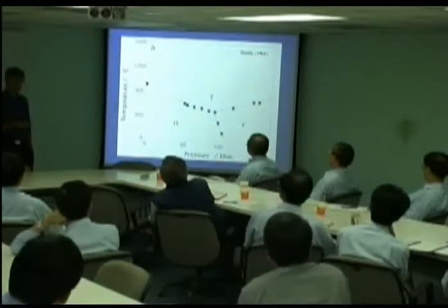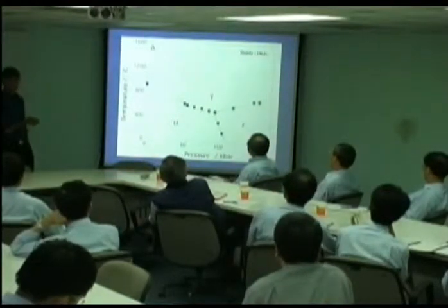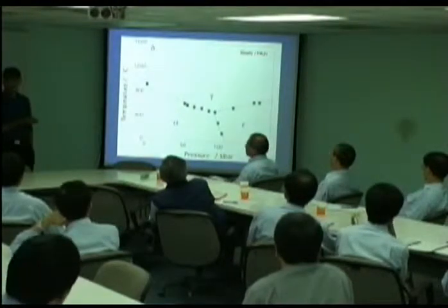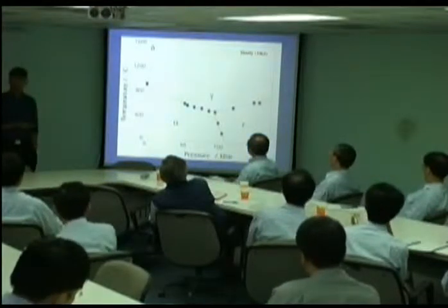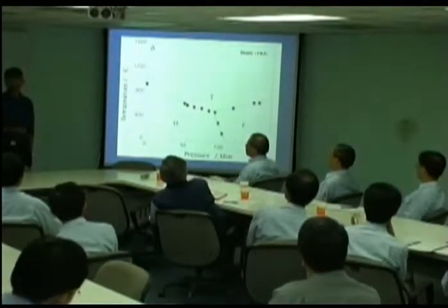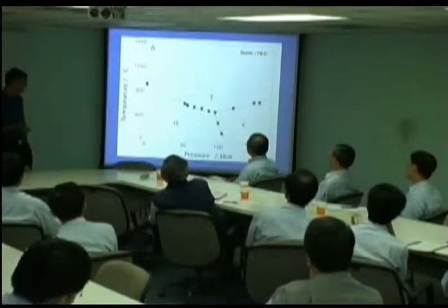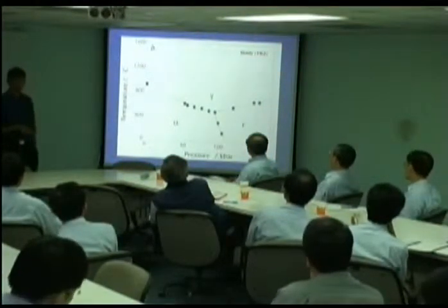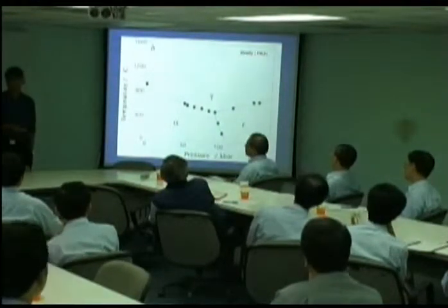And that's because there are complicated magnetic transitions in all of these phases. So even austenite has magnetic transitions in it. If I add 30% nickel to the austenite, it will become ferromagnetic, just like ferrite, because there are magnetic transitions in the austenite. If I increase the pressure enormously to 130,000 atmospheres, then I get hexagonal close-packed iron.